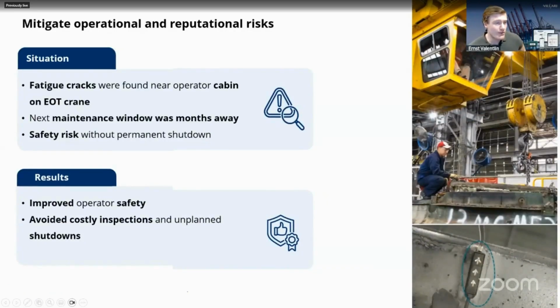So the first one we have here is a very good example of a reactive usage of our sensors. In this specific case, in a very big steel production site, cracks were found during NDT processes on the structure that held an operator cabin onto an EOT crane. In this case, an EOT crane with a very high operational pressure, meaning that a repair was scheduled for this location, but the repair was scheduled 6 months later than the point at which the cracks were found, because that was the most efficient time, the most cost optimal time to do that repair.